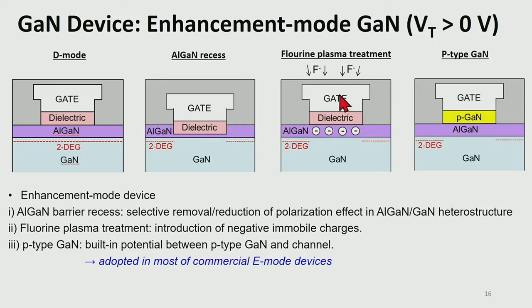The second approach is to introduce negative charges under the gate. For example, you can expose the gate area to fluorine plasma, and fluorine ions can be implanted in the AlGaN barrier, and the negative charges of the fluorine ions can deplete the 2DEG channel under the gate. So this approach is interesting, but there are some concerns. First, the threshold voltage can be dependent on the amount of fluorine ions implanted and activated in the AlGaN barrier, which is relatively thin.